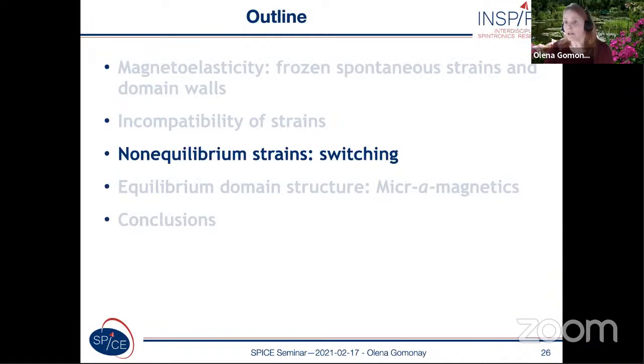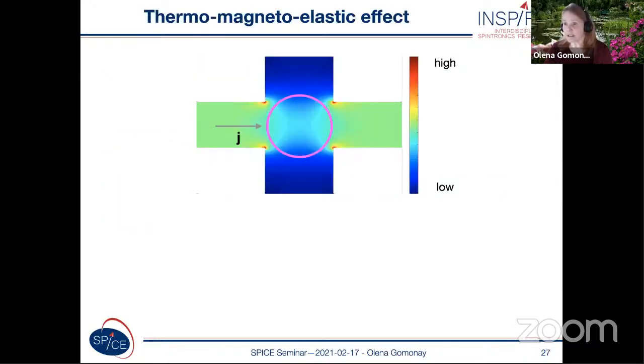So we believe that in antiferromagnets, these kind of elastic defects could be attributed to the incompatibility between the spontaneous strains, which maps a distribution of the Néel vector in antiferromagnetic textures. To give an idea how this incompatibility can work in real cases, I will discuss now some recent effects which were discovered by Chloe's group experimentally. So these are thermomagnetoelastic effects.